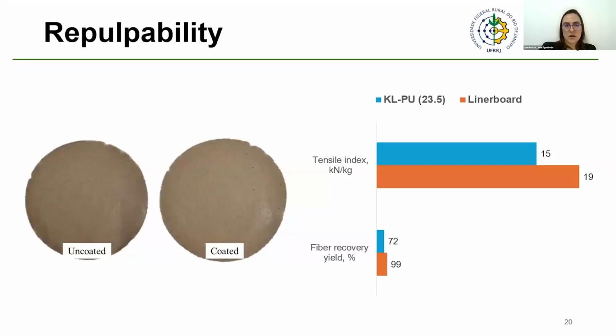Under these conditions, only 72% of the fiber was recovered from the coated samples, while for the uncoated sample, 99% was recovered. And when we tested these recovered fibers, the tensile index of the paper that was coated was lower than the uncoated paper, suggesting that probably pieces of the coating were in the paper and made the fiber bonding weak.